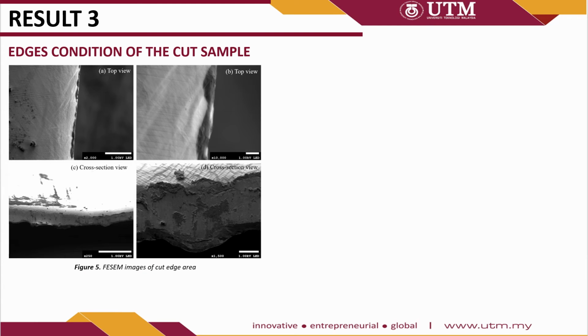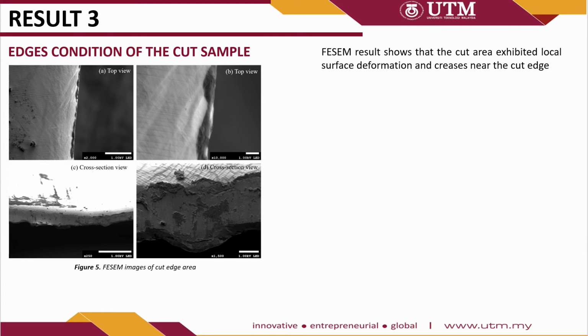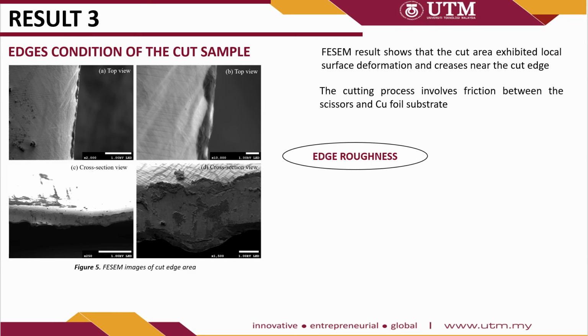Figure 5 shows the FESEM images of the cut edge area. FESEM results show that the cut area exhibited local surface deformation and creases near the cut edge, which then caused the edge roughness on the cutting surface. The cutting process involves friction between the scissor and the copper foil substrate. The edge roughness developed during the cutting process was attributed to the existence of cutting force.